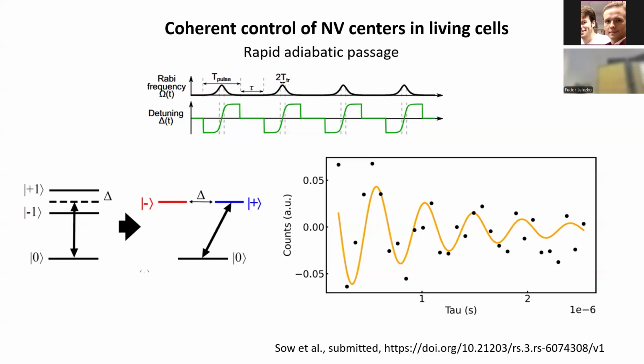Is that considered as an offset in all of your temperature measurements, or can it vary during the measurement? It's not very good to have this offset, because the absorption of the laser can change with time, and you might interpret this as heating because of a biochemical reaction, but it's not. It's better to avoid this completely, and so having a visible range laser below 10 microwatt gives us at least this artifact below 0.1 Kelvin. Yeah, that will limit the sensitivity.